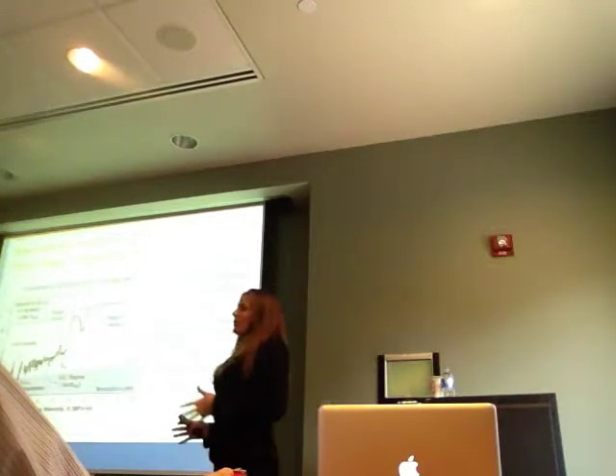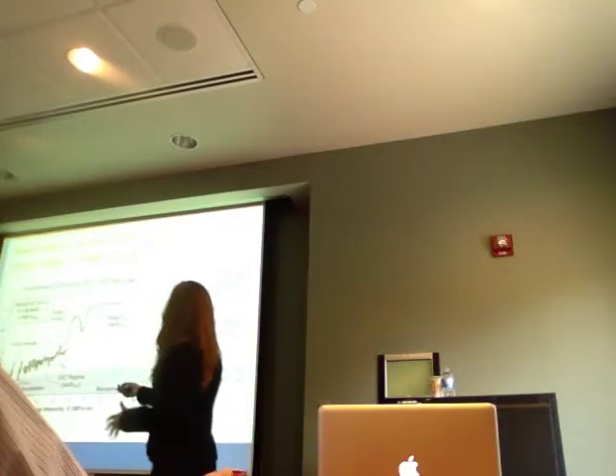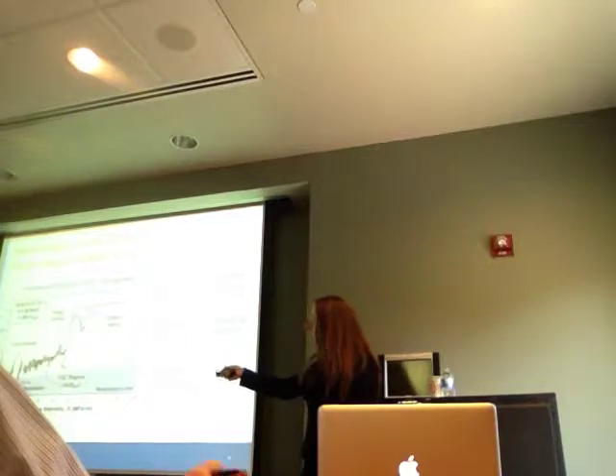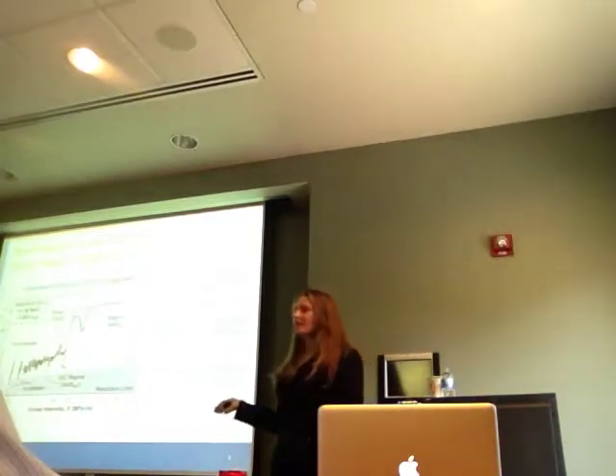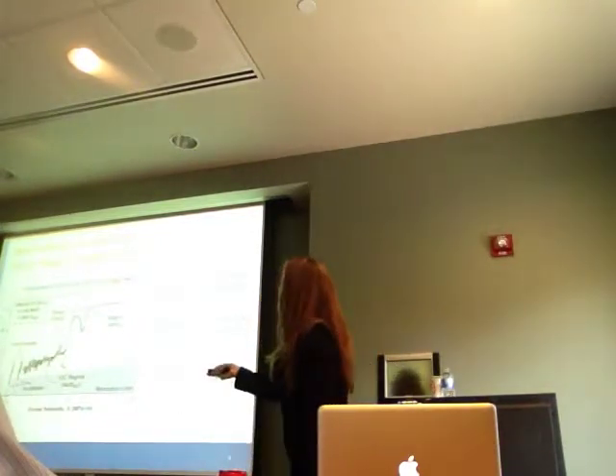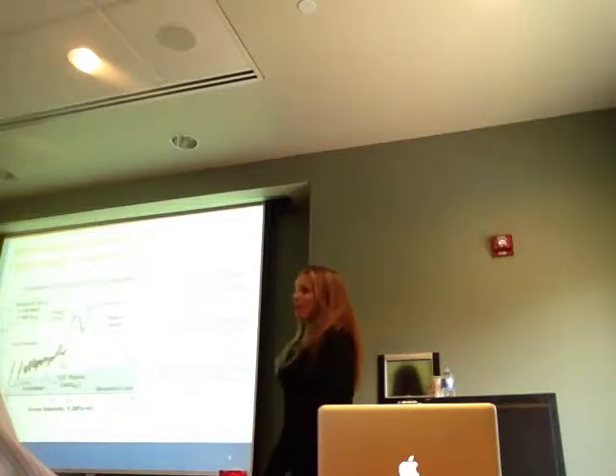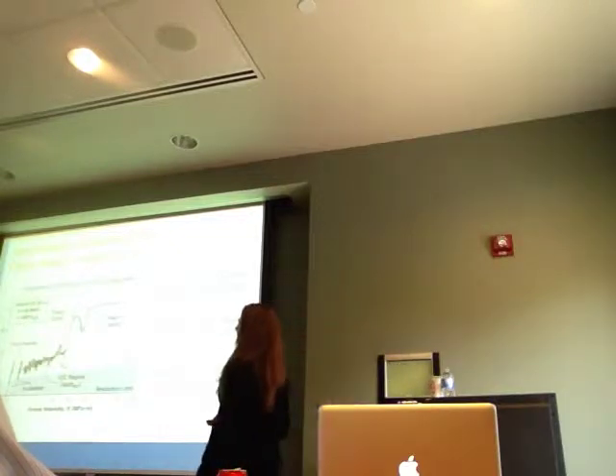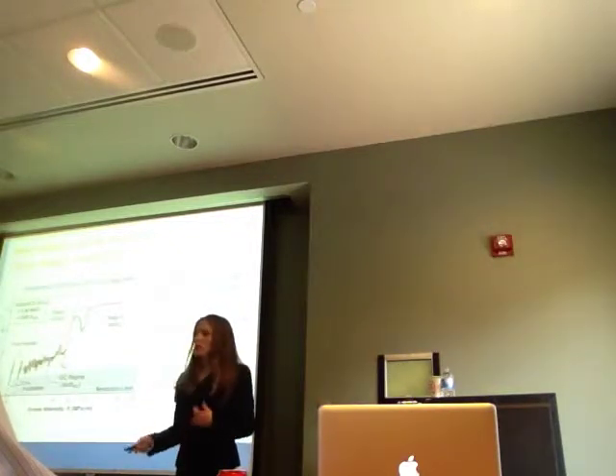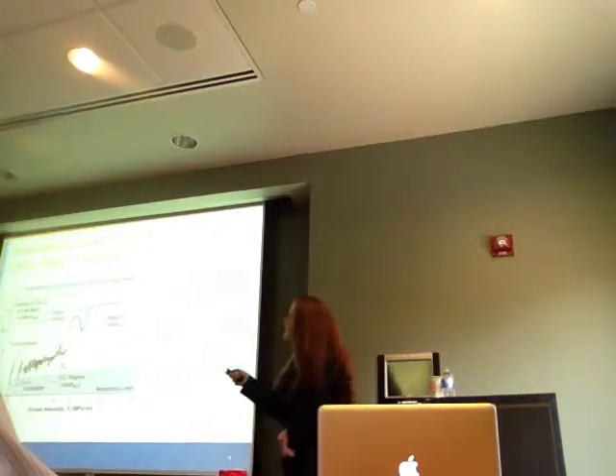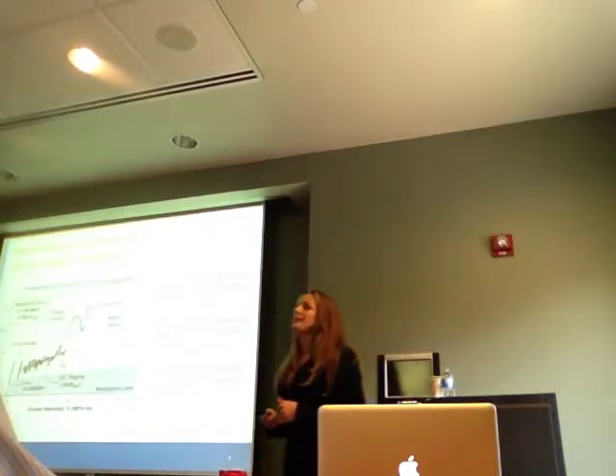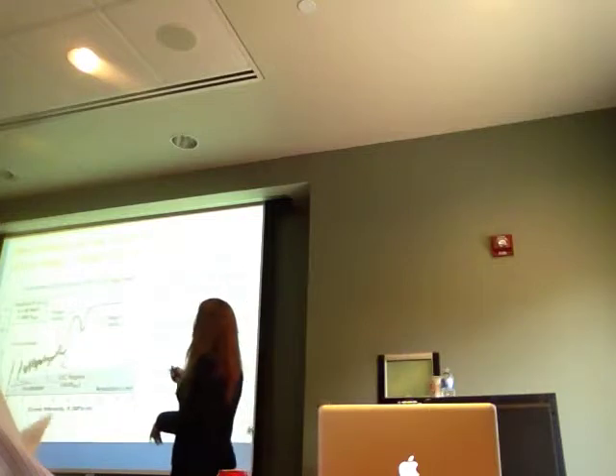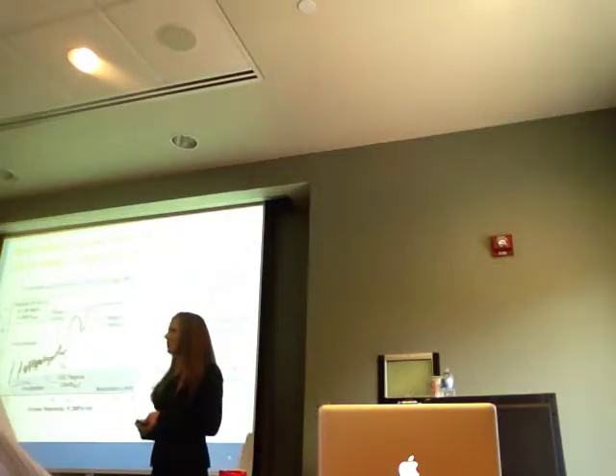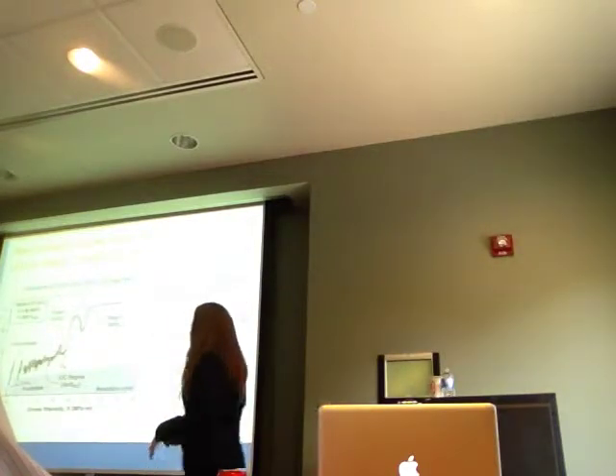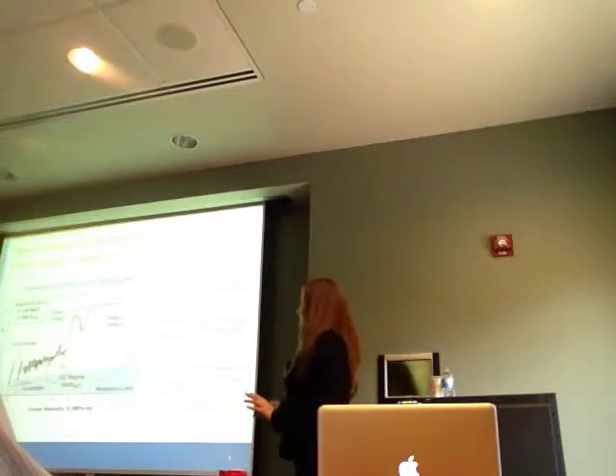So typical results look something like this. I have the crack growth rate on the y-axis, the stress intensity on the x-axis, and the resolution limit of our system in the gray. This particular data set was for a 5083 H131 specimen that was sensitized at 100 degrees C for 175 hours, giving a mass loss of about 22 milligrams per centimeter squared, so right in the middle. And you can see the stages of my test here.